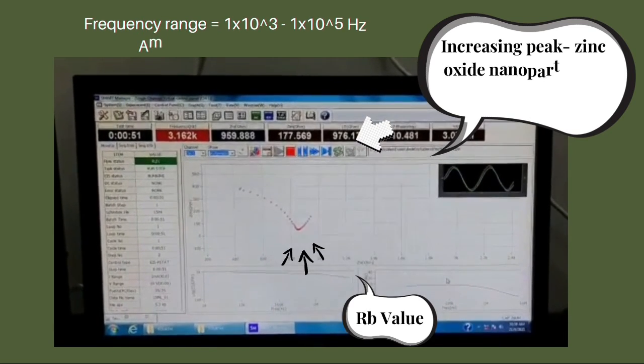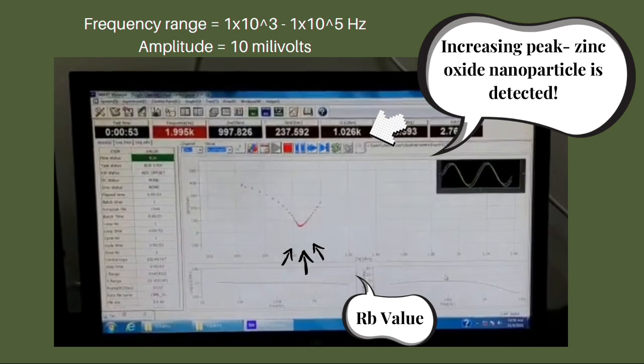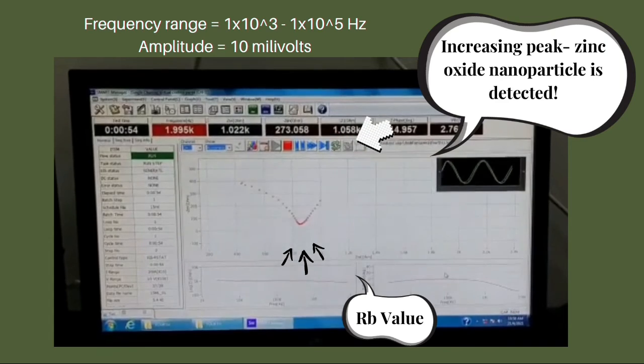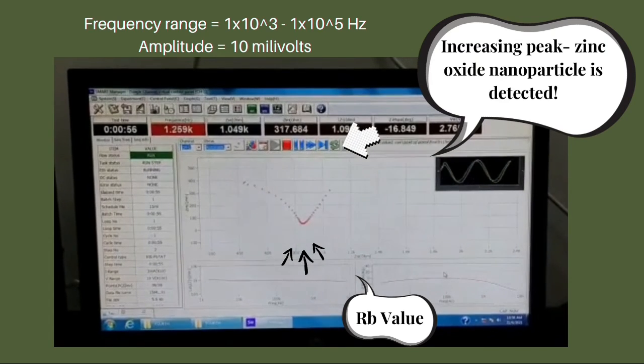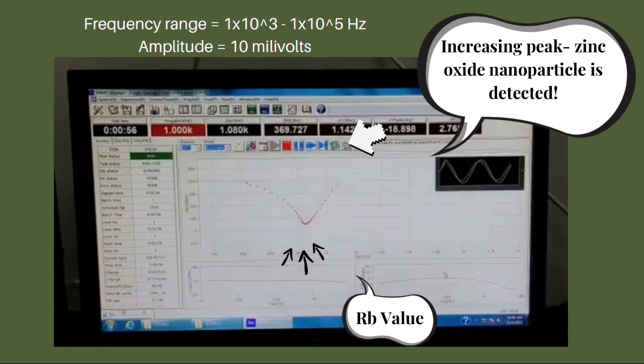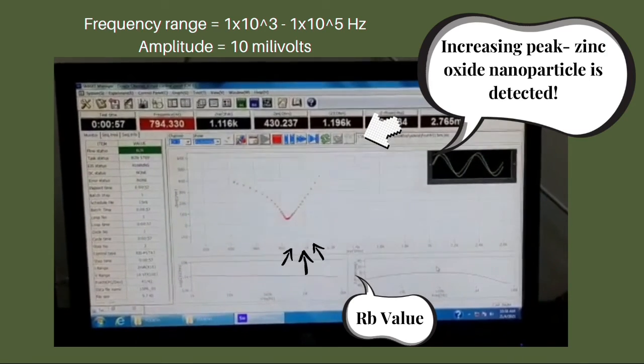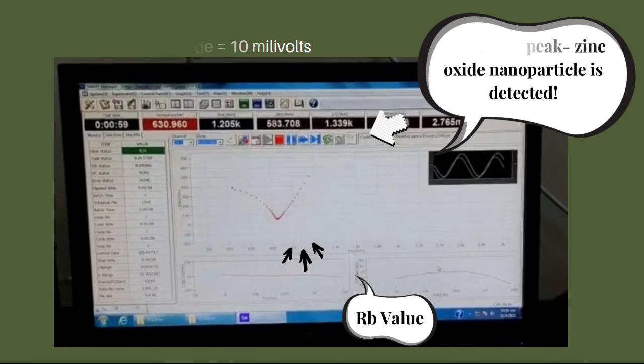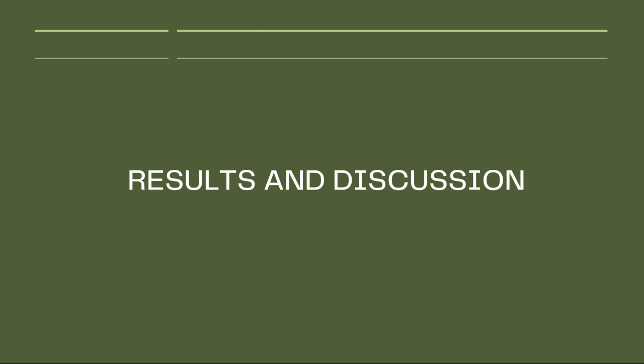The frequency range used when analyzing the sample is between 10^3 and 10^5 Hz with an amplitude of 10 mV. We can see an increasing peak at the end, which shows the zinc oxide is detected, while the region below shows the RB value, which is used for further testing.